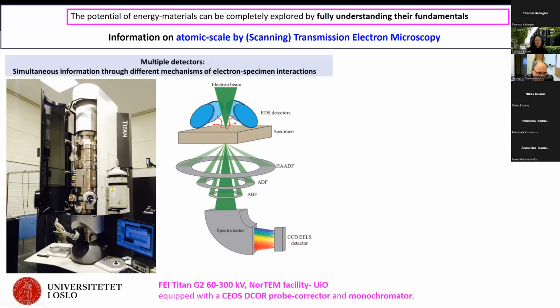Here you can see an image of our state-of-the-art microscope in our lab. It is an FEI Titan G2 operated at 60 and 300 kV. And it is probe-corrected and monochromated, meaning that we can reach high spatial and energy resolution. Also, in this simple schematic, you can see the possibility that we have to use multiple detectors simultaneously. So we can take advantage of the complementary information that we can extract through the different mechanisms of electron specimen interactions. For example, for imaging in STEM mode, we can use different detectors.